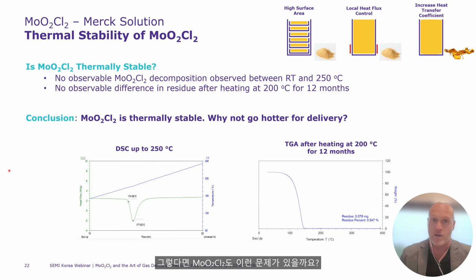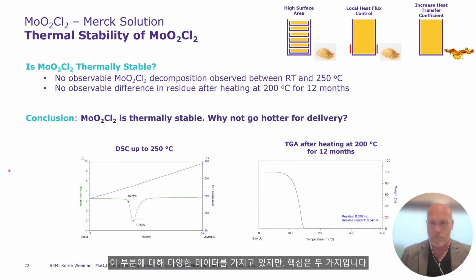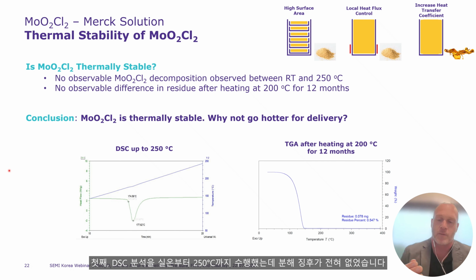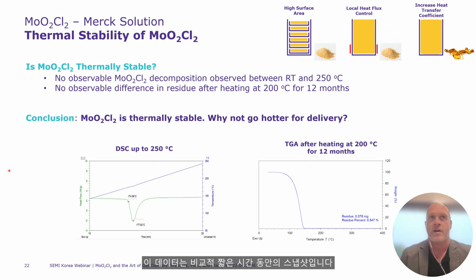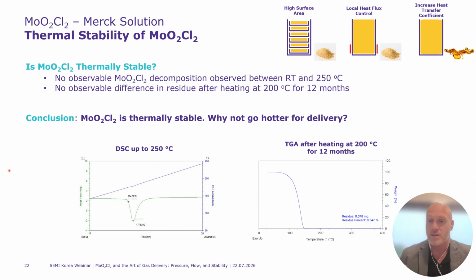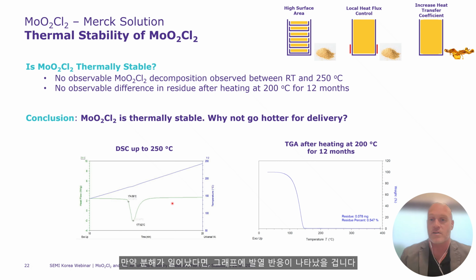So is that an issue for moly dichloride? There's lots of various data you can present on this, but two key points is we've taken DSC data from room temperature up to 250 degrees. No signs of decomposition. So this is a relatively short snapshot showing at relatively short time durations. There's no significant concern of decomposition. If there was decomposition, you'd start to see exothermic reactions happening in this green line here.